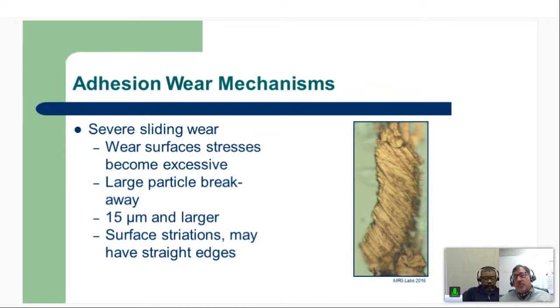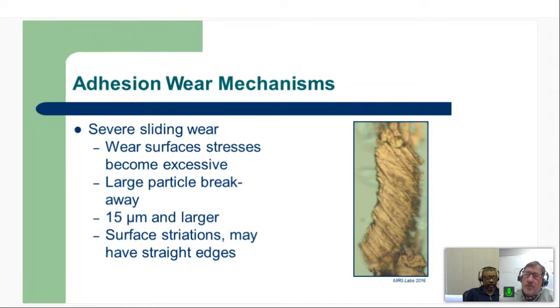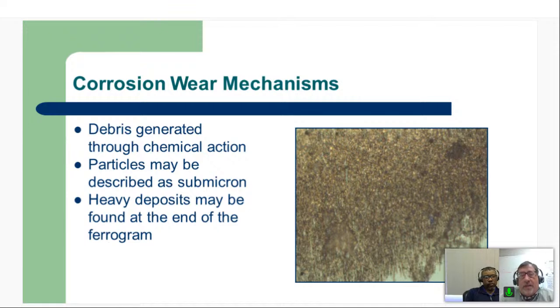That's a great point. And sometimes, Ray, you see that in the difference between, say, a turbine bearing versus a gearbox, right? Yes, just like the type of component it is tends to generate different sizes, and your action levels have to be adjusted accordingly, right? That is correct. That is absolutely correct. That's why we just use 15 to 20 microns as a layman's average of what might be an issue in terms of abnormal for wear debris. It's a starting point, but then you need to factor in what is this application, what type of mechanism, and so on.